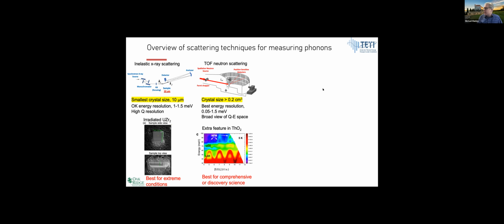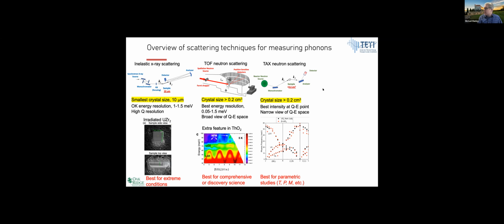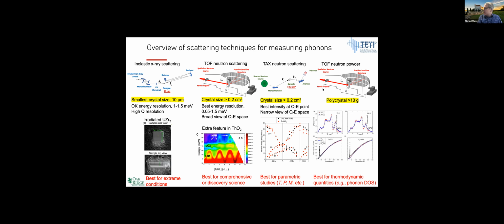Time of flight neutron scattering, which we use as well, is complementary. The bad thing is you have to use large crystals, so if you want to do something highly irradiated, it's very difficult. But in principle you can get higher energy resolution, and you get a broad view of momentum and energy space. So it's good for doing comprehensive studies of getting all the modes, and it's good for finding things because you just get a big view of everything. Triple axis is nice. It's probably the fastest for doing parametric studies. You can get data pretty quickly, but it also requires large crystals, and it only views a small amount of momentum energy space. And then, of course, finally, using time of flight powder neutron scattering, you get density of states, which is best for thermodynamic quantities and things like that.